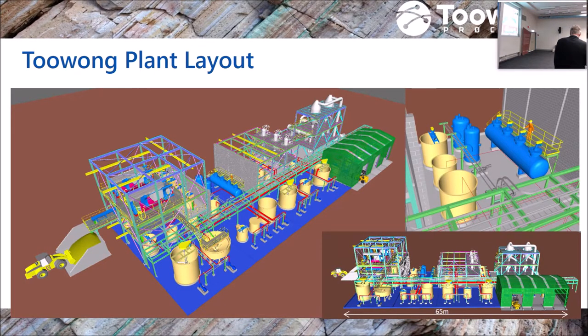Again, this is a small 40,000 tonne a year plant. This is what it would look like: reagent area, filtration coming in, filtration going out, leaching circuit, solid liquid separation, small solution autoclave. Again, it's not a complex autoclave, it's not a brick-lined titanium autoclave that you see in a HPAL circuit. It's just a solution autoclave. Evaporators and crystallisers. It gives you a feel for what a 40,000 tonne a year concentrate treatment plant looks like. It's probably about a 65 by 25, 30 metre footprint. Again, you've got to sell the vision, rather than the dream, what it looks like.